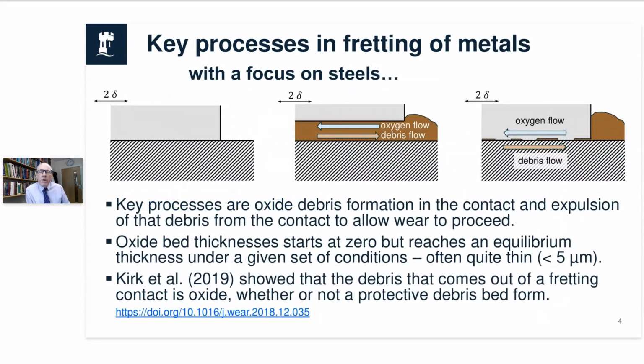Look at those three images along the top here. We start off on the left-hand side with our original contact. This is not the full contact; this might be the contact edge. It doesn't really matter. But we've got some kind of oscillation by delta, the slip amplitude there. And we start off with a metal-on-metal contact. What we all know is that after a period of time we end up with oxide coming out of the contact. If you read those very old papers, people refer to it as looking like cocoa powder. It's very, very fine, dark brown debris because it's iron oxide, Fe2O3 typically.